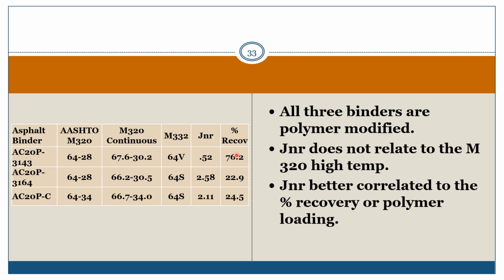there's this big difference. Here you can see there's a significant amount of recovery in this material, as opposed to the 22% or 24%. Now we have a significant amount of recovery for a Jnr value, MSCR values, and so this probably had a significant hit, causing that reduced Jnr value, even though we don't see the differences in the M320 specifications.